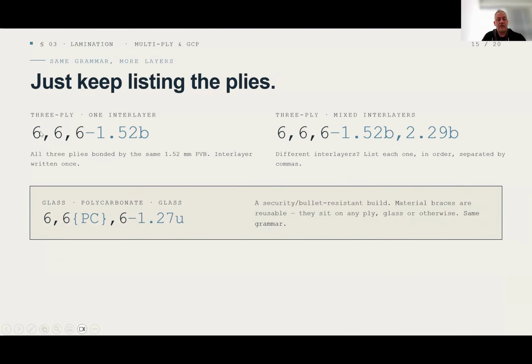So, like I said, we can do multiple. So if it's 6 mm clear annealed on clear annealed on clear annealed, but they all have the same interlayer between them all, you only have to specify it once. It's just assumed that all interlayers are this. If it's different interlayers, then after the dash, the interlayers have a comma separating them out as well. So we could say that this is a 1.5 millimeter PVB, and then the second interlayer is actually going to be a 2.3 millimeter. So if that's intentional, maybe the backlight has texture to it, and we need to thicken up that PVB so that it forms to that texture, that can be specified here intentionally. Although it doesn't have a texture because we did not put a character after it.